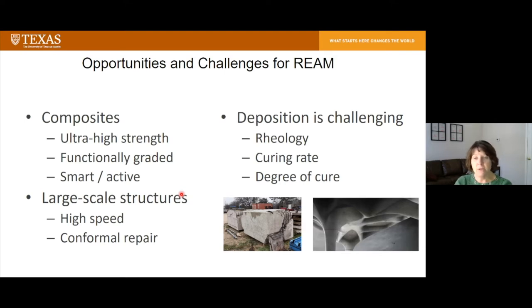Very high speed, we could do conformal repair of damaged concrete or other structures. Could create frameworks as well for depositing concrete. Deposition is challenging though, it's not an easy process. The rheology is hard to get right to be able to be printable, but still strong enough to support subsequent layers. It needs to cure quickly. And then there are exothermic temperature rises associated with that that we have to deal with as well. And we have to make sure that the degree of cure is adequate for good strength.